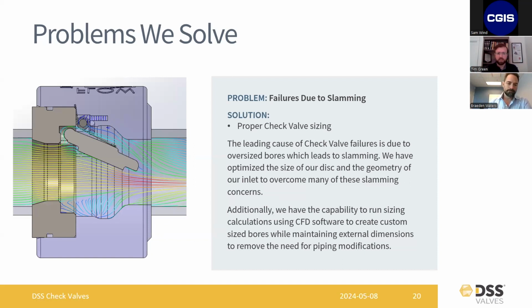So DSS has the capability to run CFD calculations and different sizing calculations to determine if the valve is seeing enough velocity to remain fully open. And if not, we can actually reduce the bore on our valve. So it's not uncommon to see a DSS valve with a reduced bore, which seems counterintuitive. You're blocking the flow area.